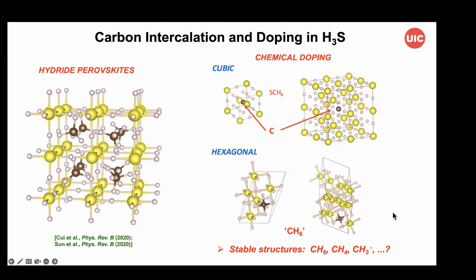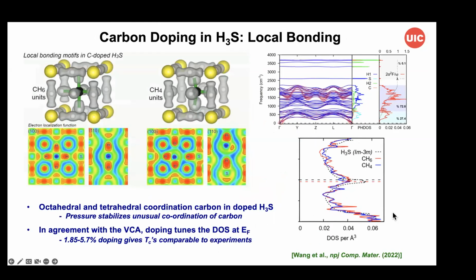But this motivated further study of actually looking at doping and then asking the question, what's the nature of the carbon in the system locally? Do you have defects? Do you have methane-like structures, or do you have carbon in octahedral coordination by hydrogen, which is quite unusual? And in looking at this, some calculations that were just completed.